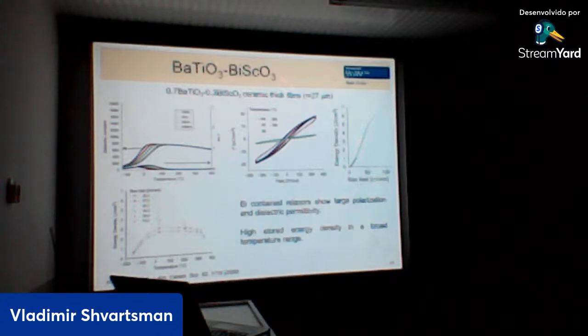Other materials, for example, people from, I think, Penn State studied the system of barium titanate with another bismuth compound, bismuth scandium oxide, and they have thick ceramic films with a thickness of 27 microns, and they can reach high energy density with a field of 1000 kilovolts per centimeter. So they can reach about 7 joules per cubic centimeter. What was also interesting is that this high energy density was stable in a broad temperature range, which is very important for the application. You should not have these large numbers only in a narrow temperature window. For application, the material also has to work stably in a broad temperature range.